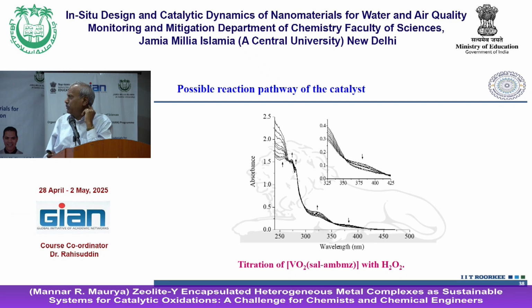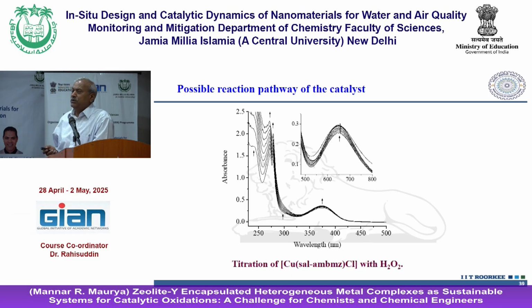Similarly in the copper complex, not a very encouraging result, but you could still see spectral changes here, but no isosbestic point in this case, because copper peroxo formation is not straightforward. There, peroxo is mostly known to form through a dinuclear compound, like two species coming together and forming, so you will not get a very encouraging result, but still some spectral changes can be seen.